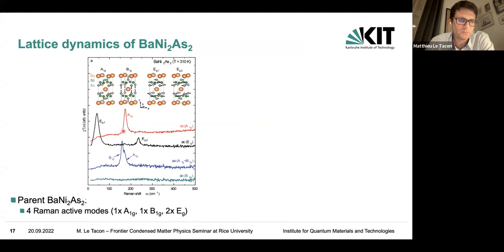So there's an A1G mode which corresponds to vibration of the arsenic atom along the c-axis, the nickel mode which has the B1G symmetry, and you get the 2 EG phonons that you see when you put your polarization, so cross polarization, on the edge of the sample. So that's why it's a bit tricky, because normally these samples are not very thick.